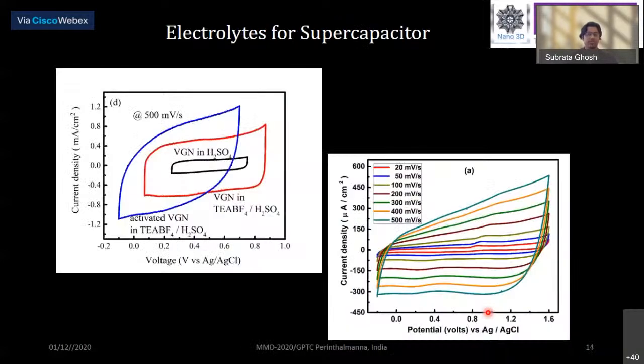Okay, as I told you, another component of the supercapacitor is the electrolyte. We used VGN, vertical graphene nanosheets. As I told you, graphene is a single layer of graphite, and here the graphene is standing vertically on the substrate. We explored it in H2SO4 solution. We made 1 molar H2SO4 aqueous electrolyte, and you can see the area under the curve is very small. But when we use TEABF4, an organic salt, combined with H2SO4, we can get a higher window and more charge storage capacity.